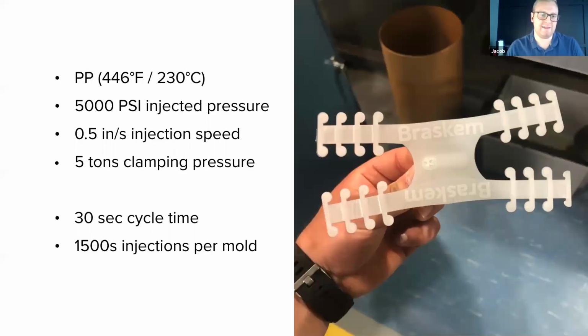And the key trends that we've outlined previously and restated here with some actual numbers is low pressures. In our case, we're using about 5,000 PSI injection pressure. This is definitely going to be dependent on the part we're trying to make, but starting low and going as high as you need is the trend you should go. Injecting slow, reducing shear. You don't want to pack material very fast into these cavities and develop high shears. We inject very slow. We're not processing as quickly, but we still get the part in a reasonable time. Clamping pressure is critical. Keep as low as you can. Since we're not packing out with super high pressures in these molds, you don't need as much tonnage to keep the plastic in and prevent it from flashing.